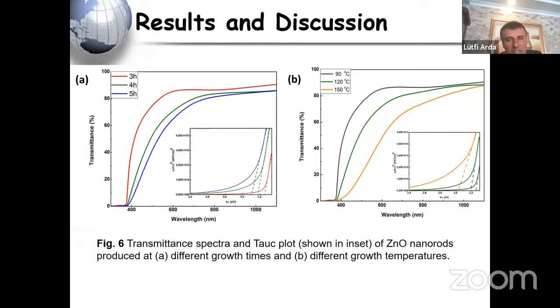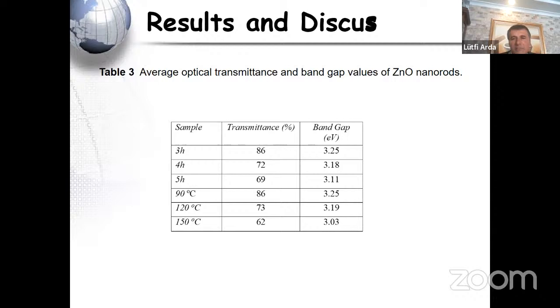After transmittance, we calculated the band gap of the nanorods using the Tauc plot method. I showed you the band gap here. Look at the band gap of the nanorods. It decreased with the growth time and decreased with the growth temperature. After this, this is about the optical properties and the last measurement.